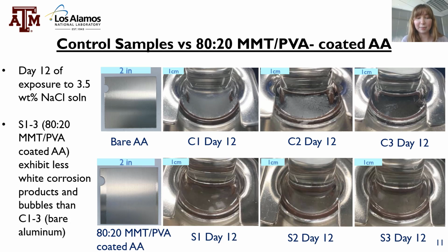So as you can see in the top row, especially in control samples 1 and 2, after 12 days of exposure to the electrolytes, significant amounts of white corrosion products have formed, as well as oxygen gas bubbles. However, as you can see in the bottom row, for samples 1 through 3, even though there is a little bit of white corrosion products, the coating has protected the aluminum alloy from forming significant amounts of corrosion products, and there are almost no oxygen gas bubbles.